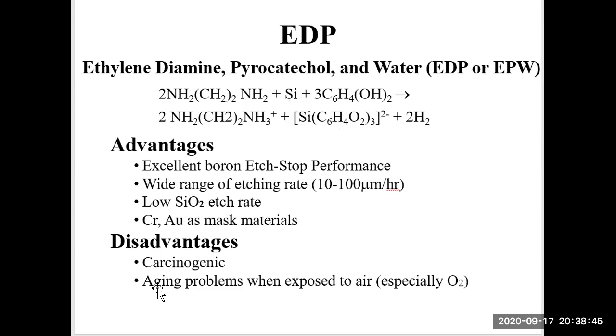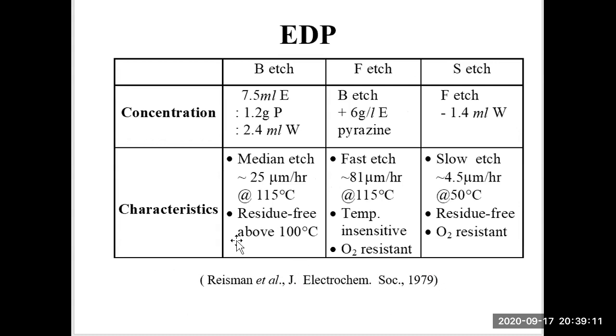Another disadvantage is its aging problem when it's exposed to air, especially oxygen. Namely, the etching rate may change or decrease in air. This table summarizes some EDP recipes: B etch, F etch, S etch. B is the basic recipe. F means a fast etch, so it has a higher etch rate compared to B etch. S etch is a slow etch, so its etch rate is very small.